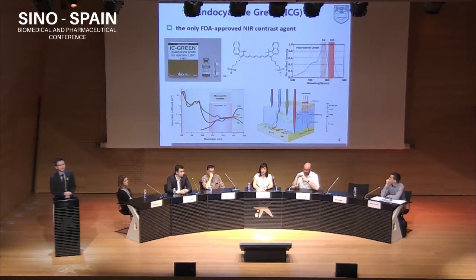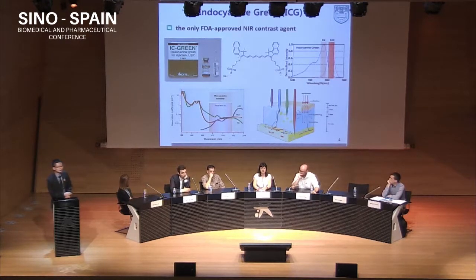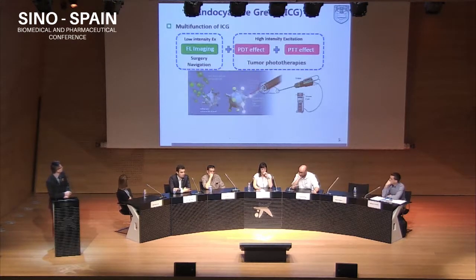One of the contrast agents used for NIR imaging systems is indocyanine green, short for ICG. It's a tricarbocyanine dye. Its excitation and emission wavelengths are located in the near-infrared range, from about 780 nanometers to 820 nanometers. In this range, the light penetration depth into the tissue is the highest, and the light that excites the dye and the light emitted from the dye can be easily detected by the systems.